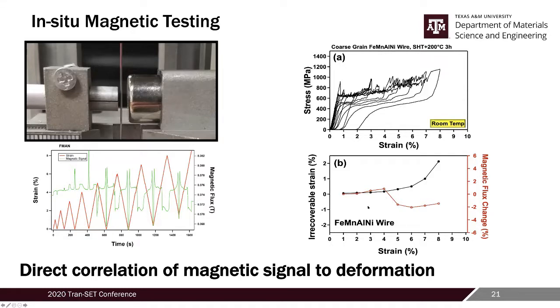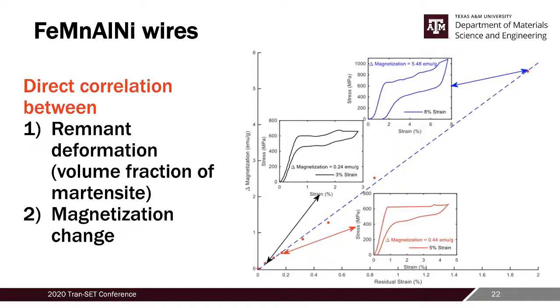Here we show this change using in-situ experiments. And again, we established a direct correlation between this remnant deformation, which is the volume fraction of the martensite in your material, and the magnetization change. Using this property, you can use these materials as self-sensing elements in civil engineering applications.